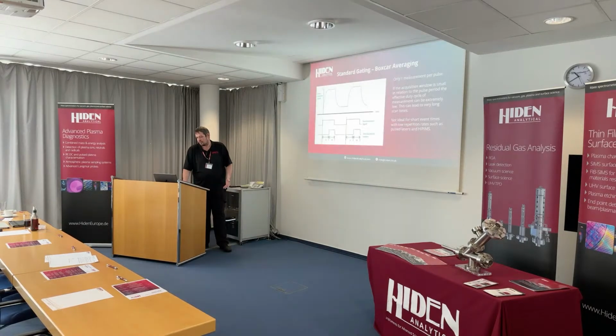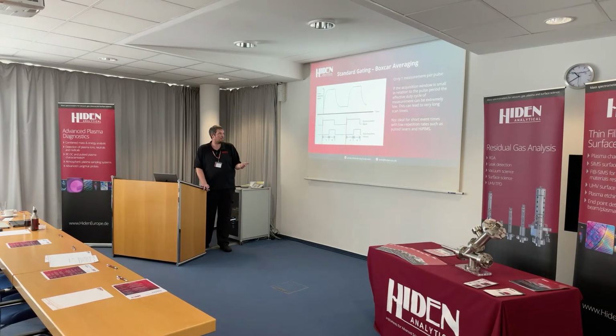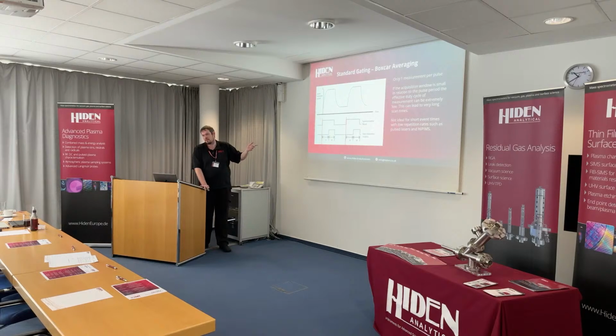The standard gating that all instruments are supplied with is a boxcar averaging technique. We supply the instrument with a synchronization signal at the plasma frequency, and then we choose a window of time within the pulse where we can acquire the data. We can change the position and the width of the pulse with the 2 parameters.